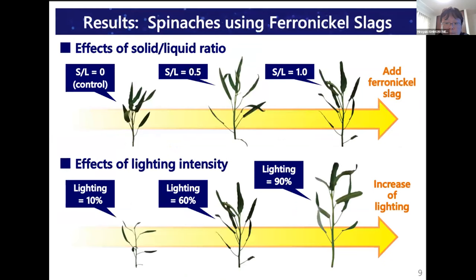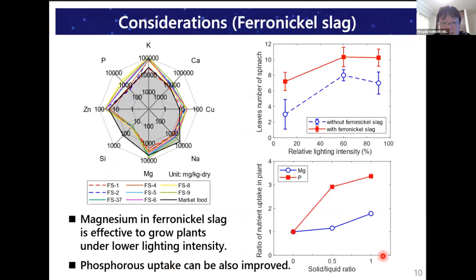In contrast, here is the result of Chinese spinach with ferronickel slag. Spinach grew with ferronickel slag and lighting like this. This is a detailed consideration. The left shows a difference in chemical composition between grown spinach and a market one, the gray hatch. Even if the chemical contents are not more than those of the market one, the Chinese spinach grew healthily in appearance.